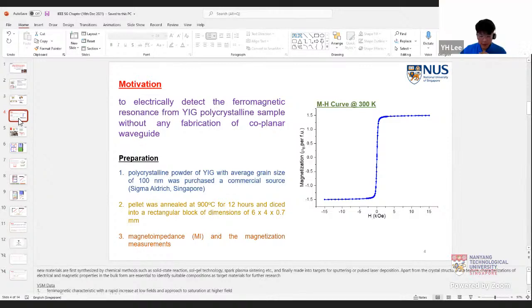Initially, I didn't really conclude it as a ferromagnetic material. It is just that usually a typical magnetization curve, to my level of knowledge or understanding, lets us conclude either paramagnetic or ferromagnetic. So my initial conclusion was that it was ferromagnetic. But upon careful discussion, my supervisor told me that YIG is actually ferrimagnetic at room temperature. So he suggested that I look at a few literature readings. While we were preparing a similar manuscript for submission, the editor also highlighted that we should state that this is a ferrimagnetic sample instead of ferromagnetic, though the data is the same. So it's because of the structure, yes.